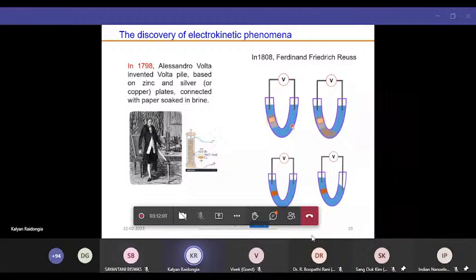It gives an indication that all these solid particles, which initially were considered neutral, actually have an electrical charge. Otherwise, they would not have moved in response to an electrical field. Similarly, he did another experiment where he made a filtration setup, a plug of clay minerals or soils. Then he applied the voltage. Then he could see that the water level was rising on one side and decreasing on the other just by applying voltage. This is now known as the electroosmosis process.